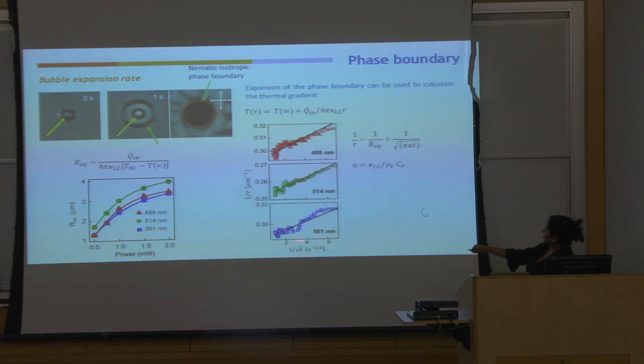You see the time is less than, this thing forms within milliseconds. So we use a high-speed camera there. We are plotting R as a function of 1 over t. Fit a straight line. The slope can give us alpha. So this sounds like a strange thing to do, but here's why we do it. We can calculate alpha. These are properties of the liquid crystal that's available in literature. We can get alpha from the slope here.